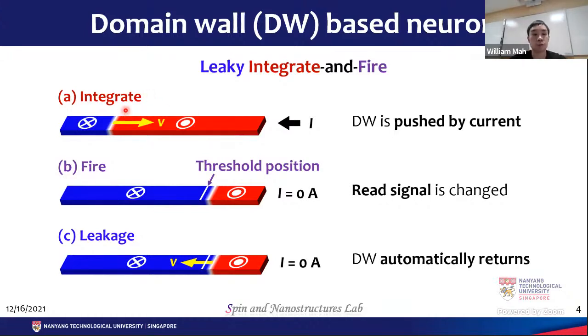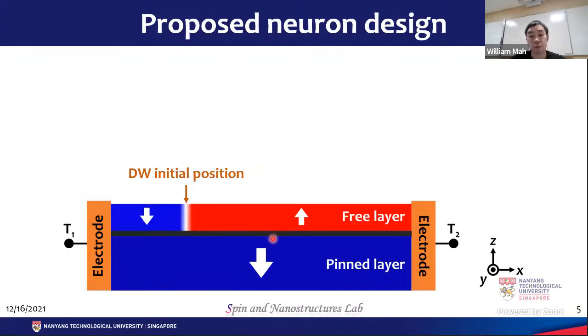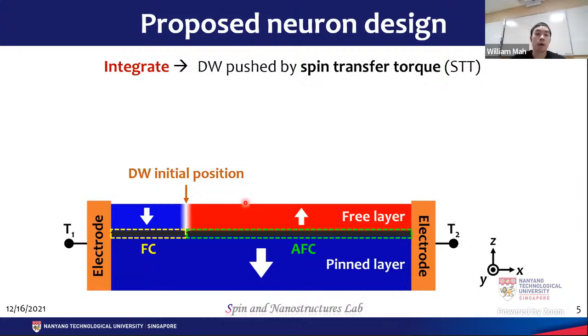In my research, I want to first achieve the integrate and leakage functions. I can do that by utilizing a synthetic antiferromagnetic structure where the free and the pin layers are mostly antiferromagnetically coupled to each other. I say mostly because there is a region on the left which I want to be ferromagnetically coupled, because then I can nucleate the domain wall without having to apply any magnetic field. I achieve the integrate function by applying current and pushing the domain wall towards the right via spin transfer torque. Once I switch off this current, due to the antiferromagnetic coupling between the top and bottom layers, the red domain expands, which automatically pushes the domain wall towards the left, back to the initial position. That is the leakage function.